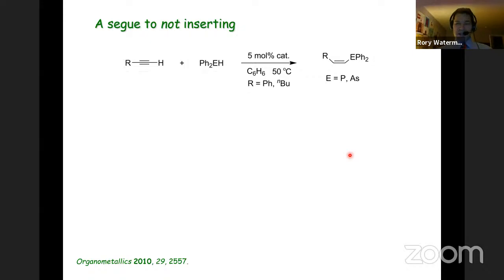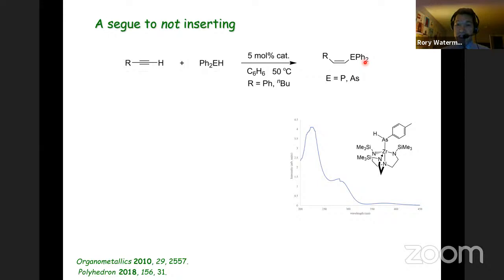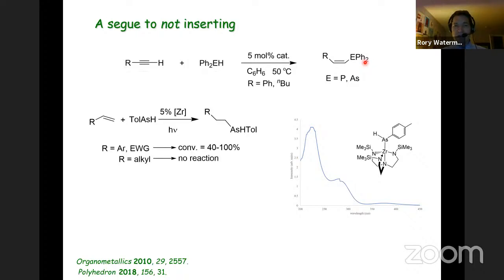So again, this is the same reaction I showed you a minute ago, and I alluded to hydroarsenation. And while we're not talking a lot about hydroarsenation, it is a reaction that comes up now and then in our lives. And so for the arsenido derivative here, I show a crude UV-vis spectrum of the tolyl derivative of zirconium. It can undergo hydroarsenation, and in fact, we see modest to good conversions for styrenes and better conversions for Michael acceptors. And for unactivated alkenes, there's no conversion whatsoever.